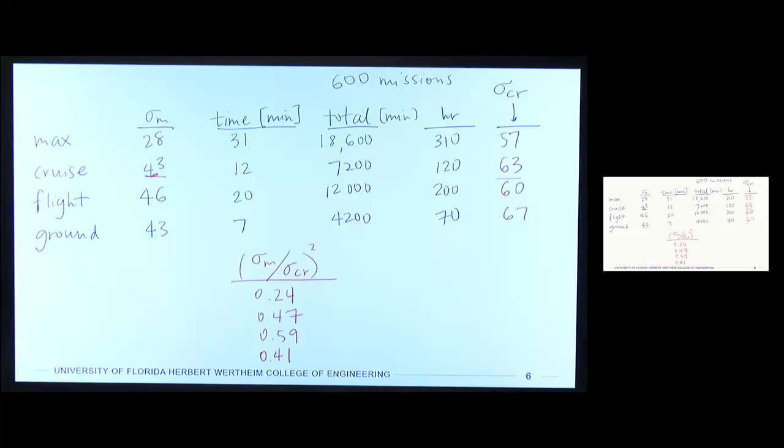So the sum of those two, which we will compare to a value of 1, is 0.58, 0.54, 0.75, and 0.43. Okay, so a comment here on these values. We were checking to see if any of them went higher than 1, because that means that that power setting, as we've identified it, would cause a failure.